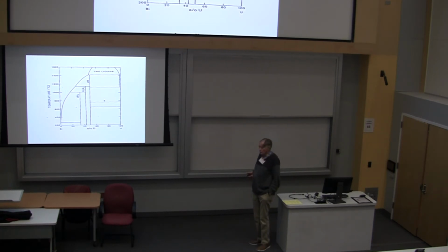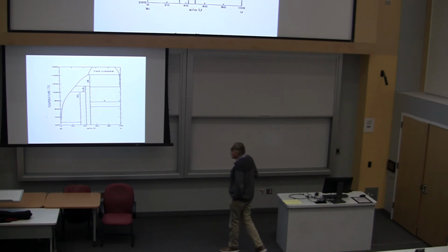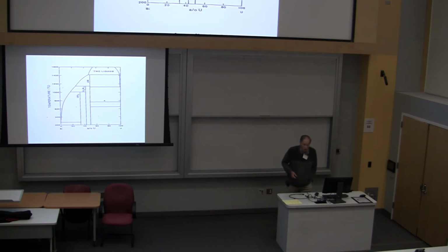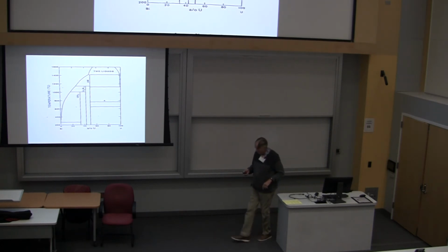And I heard from a friend of mine from Oregon, a guy called Al Arco, that they'd actually managed to grow some uranium compounds using molten bismuth. And so the idea, here's a uranium bismuth phase diagram. And you can see in here that there's a lot of solubility of uranium out here in molten bismuth. And so I thought, well, gee, maybe I can grow uranium platinum 3 out of bismuth. And I tried it, and sure enough, you got these beautiful needles of hexagonal stuff.